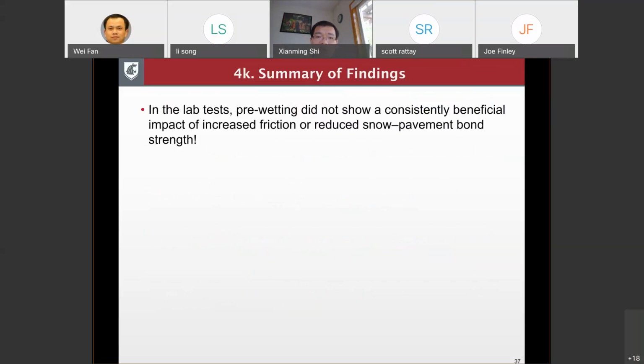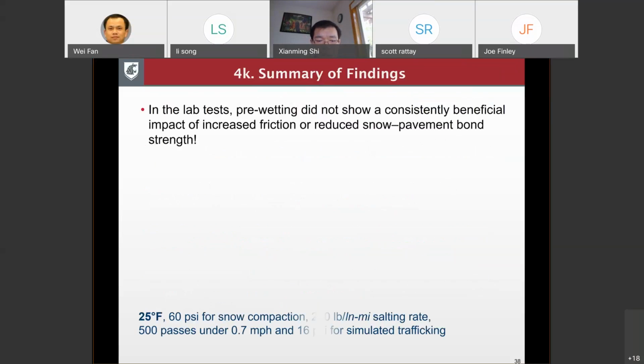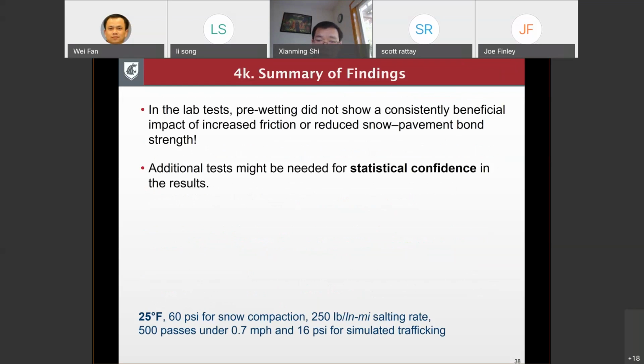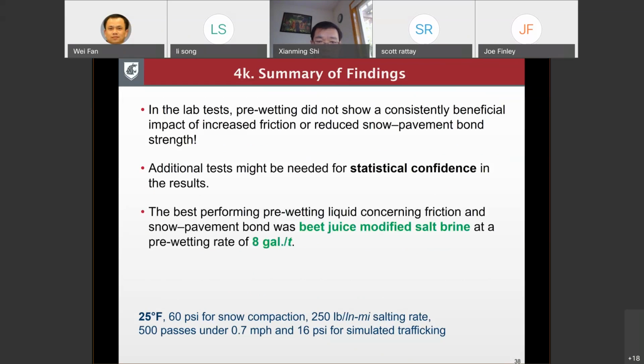Also, in the lab test, pre-wetting did not show a consistently beneficial impact of increased friction or reduced bond strength. That's interesting. And again, a disclaimer is that we only have 500 passes and this very low speed, and the pressure was only 16 psi instead of a typical, maybe 50 or 70 psi by trucks. And additional tests might be needed for statistical confidence in the results. And the best performing pre-wet liquid, if we're looking at friction and pavement snow bond, was beet juice modified brine at 8 gallons per ton.